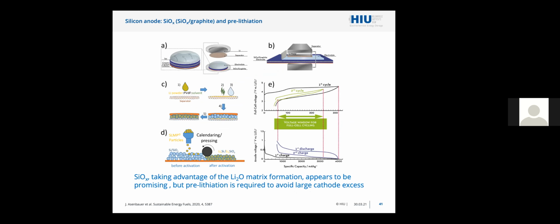On the other hand, the fact that we have to transform the oxygen into the lithium oxide requires consumption of lithium. And again, don't forget that in a conventional lithium ion cell, all the lithium comes from the cathode. So there are a lot of activities now going on about pre-lithiation, which is extremely important. You add more lithium into the cell to avoid the loss of cell performance due to the consumption of lithium during the formation. And this is done in several ways. There could be the use of a sacrificial lithium metal electrode inside the cell, as well as the addition of lithium powder during the cell assembly, for example, depositing lithium powder on the separator or on top of the negative electrode, as it is indicated in the slide.